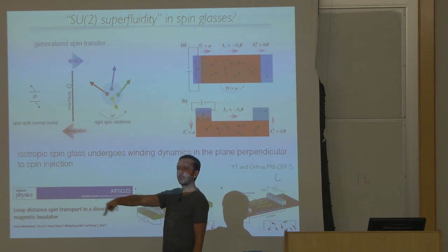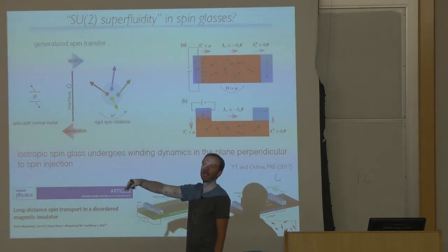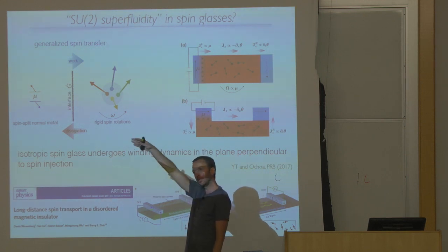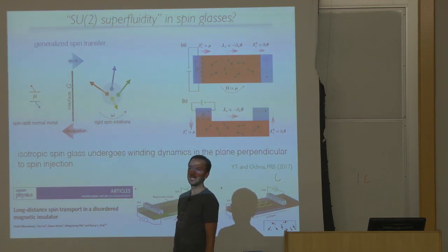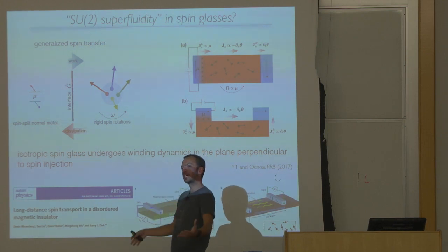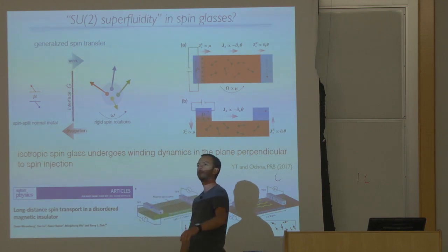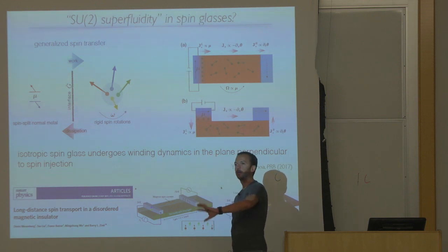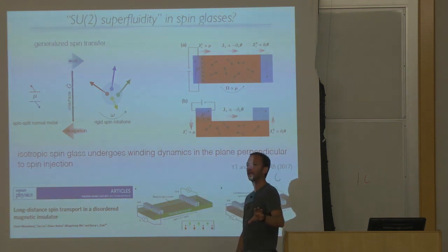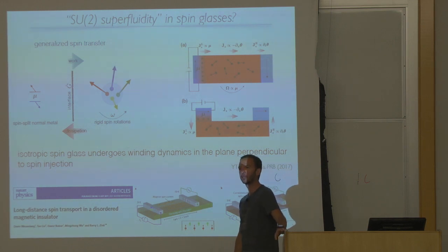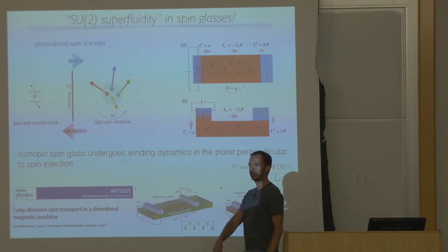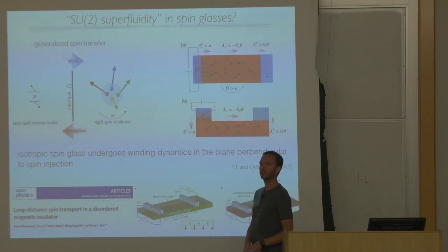And then the phase slip rate would be thermally activated. So the parasitic normal dissipation would be proportional to e to the power minus this energy over k_B T at finite temperature. At zero temperature, it doesn't freeze out completely; there are some remnant quantum phase slips. This physics could be mapped onto what people already know in superconductors. So we've done that. We have a paper on thermal phase slips and quantum phase slips, and you could basically proceed by mapping onto superconductors.